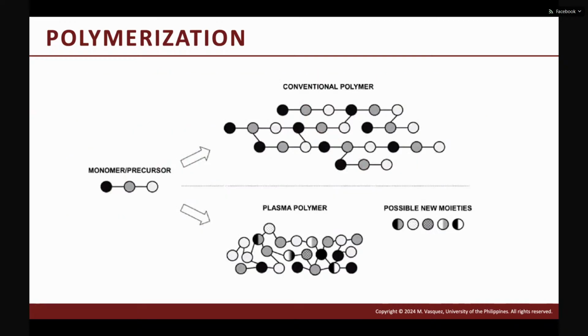Another important thing that you can do with plasma polymerization is that you can actually create a new plasma-polymerized film. If you have a precursor, you can fragment this precursor and use that to form another type of film or another type of layer, and you can produce different moieties as compared to the conventional polymers that you usually make out of these precursors. But there will be a lot of tuning of the different parameters. You have to understand how these monomers are fragmented and so on.